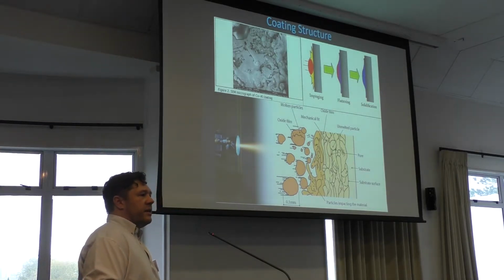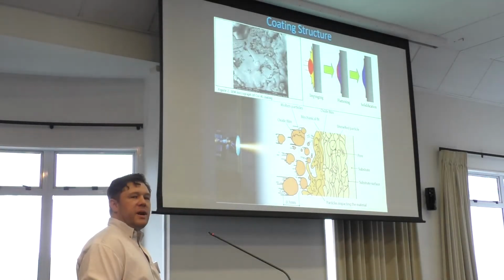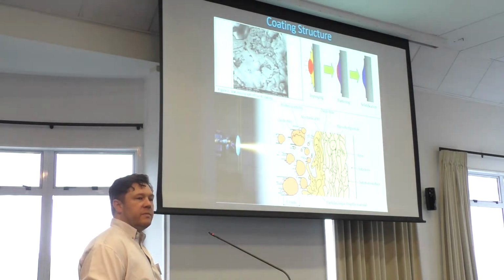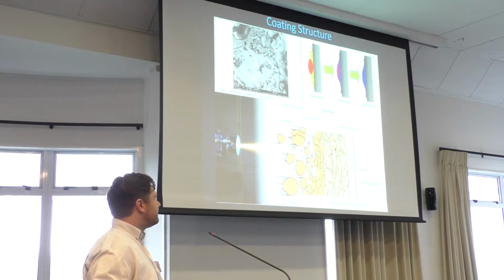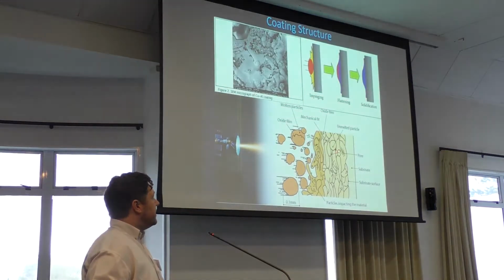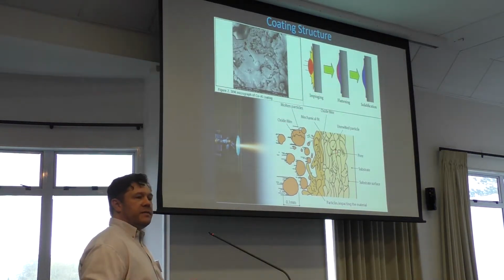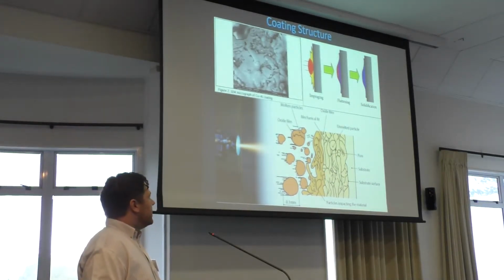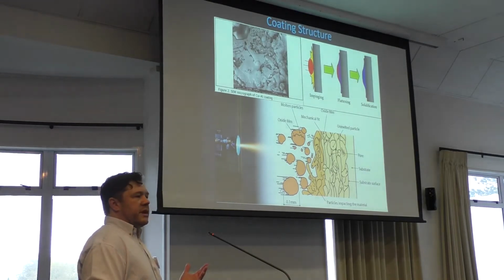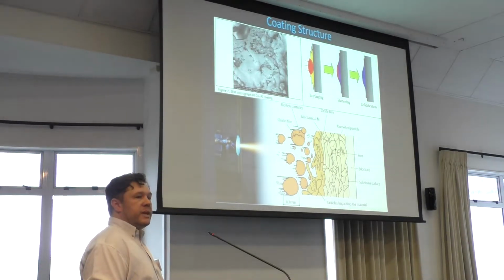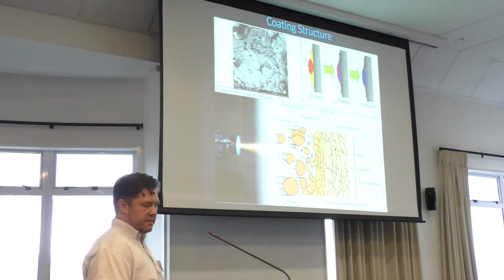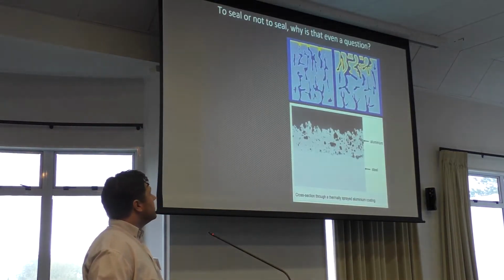When it comes to cathodic protection, the unmelted particles aren't really too much of an issue. We've got full metallic contact, so you're still going to have an anode within that coating from that particle. But the porosity can move against us or for us, depending on which situation we have. Generally, we want to seal it to prevent premature activation of the coating, if you like, but it's not necessarily something we have to do.